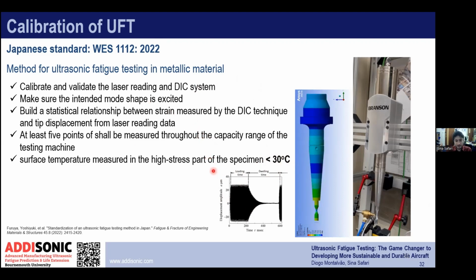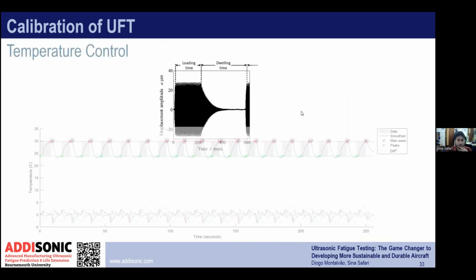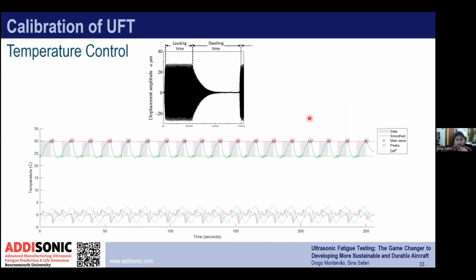So this figure here is just showing how the test is working. We just excite the machine. It starts vibrating at 20 kHz. Then the cooling system starts and the machine stops vibrating. As you can see, we have a very quick decay response, and the vibration dies down and the cooling system works, and then after cooling it just starts again. So in the next slide I'm going to show how the cooling system is working in practice in our lab.